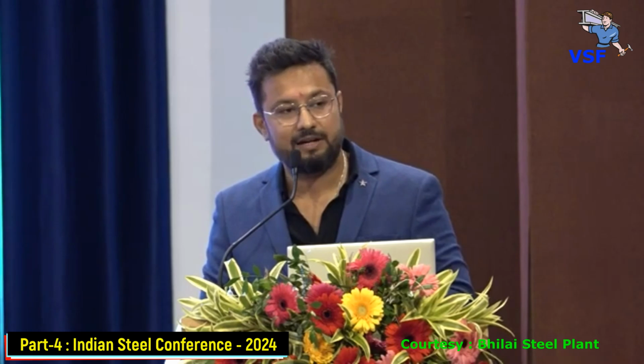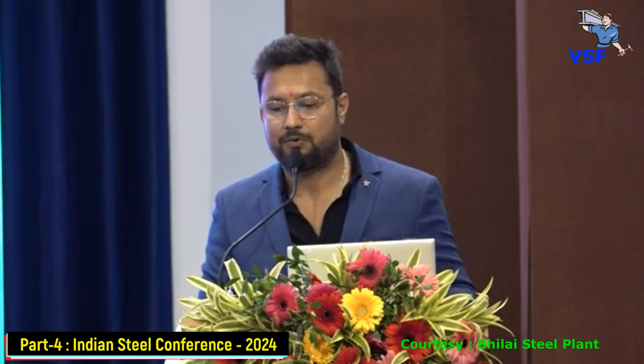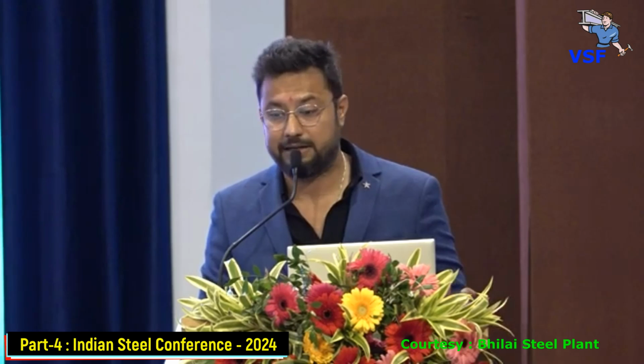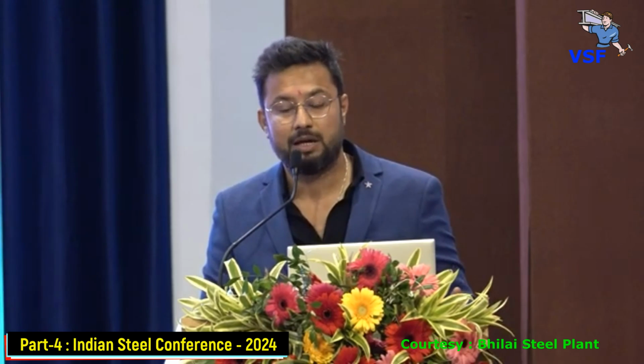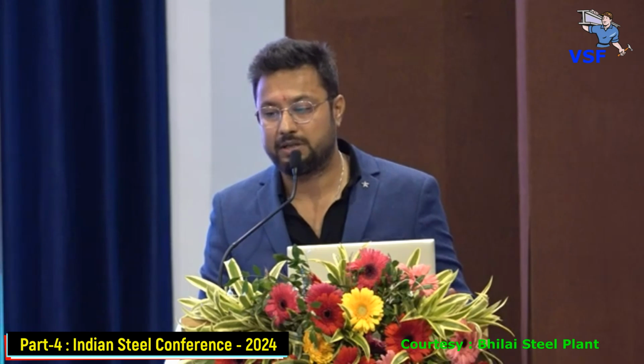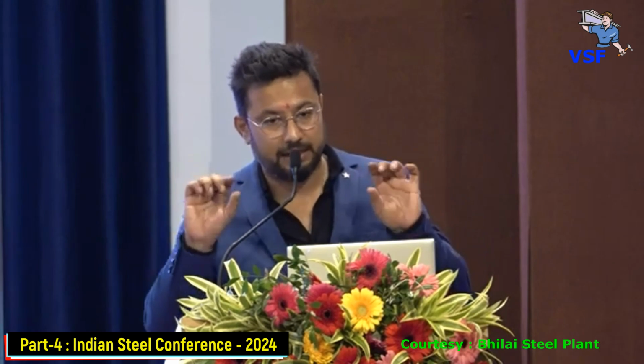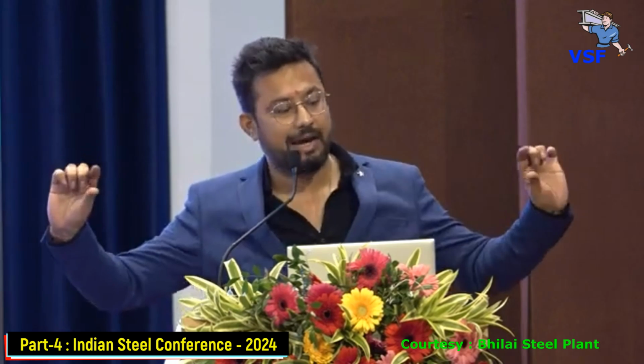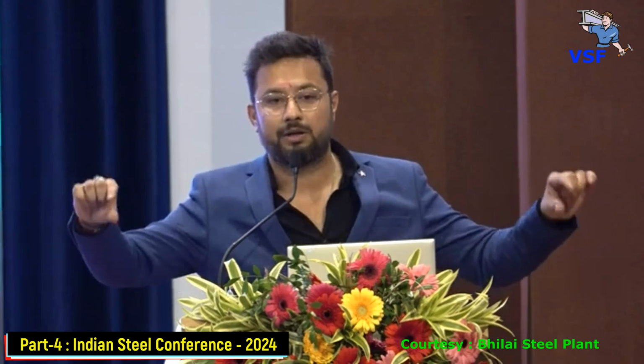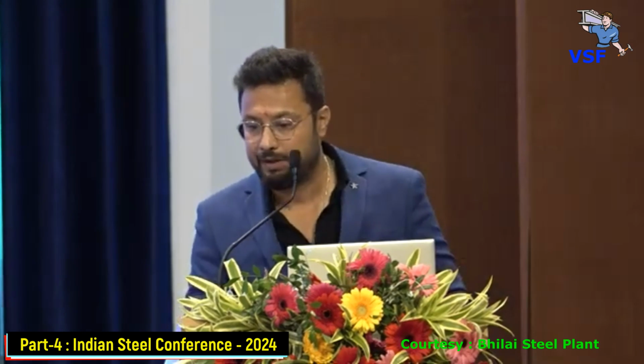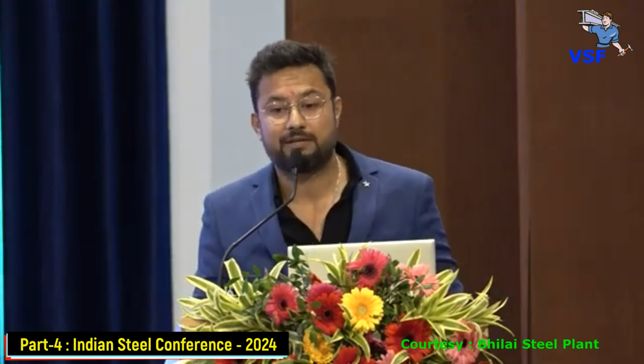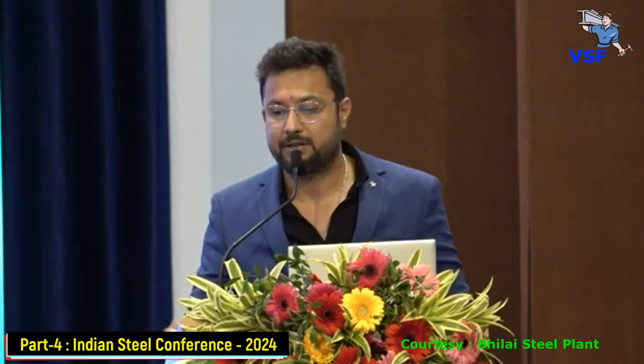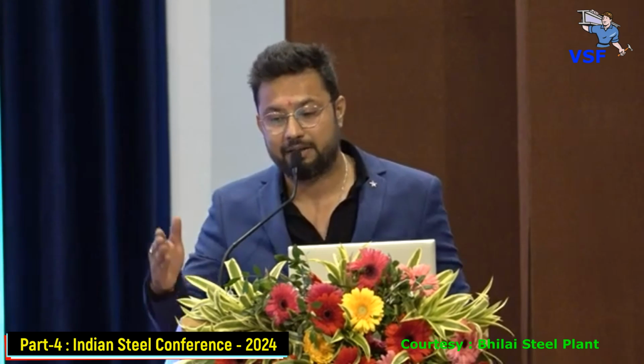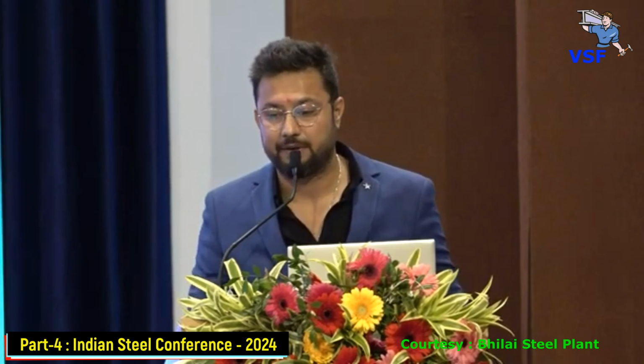These are some of the significant benefits we have in our system. Of course, operating cost wise, it's very low, approximately 1/3 compared to the air blow system. Then we have uniform cooling, because in this system we are taking the entire length of the rail and dipping it together in a water polymer bath. Then, of course, the cooling rate flexibility. Because of the deep penetration, we are able to also get results up to 13 degrees per second.